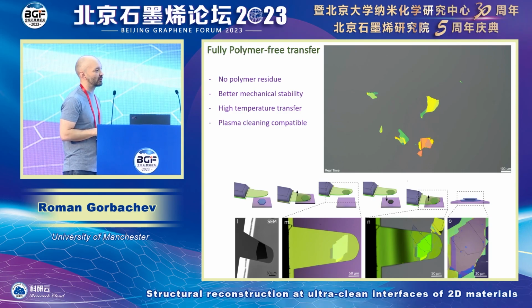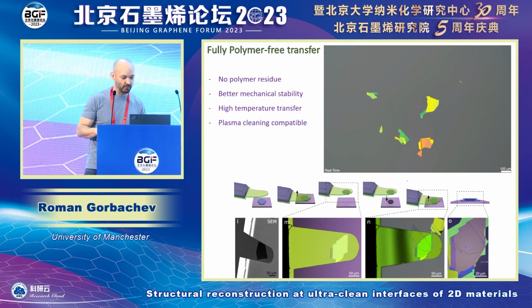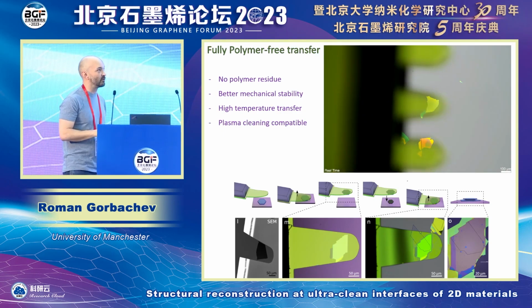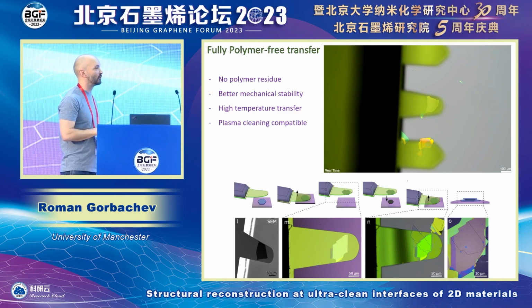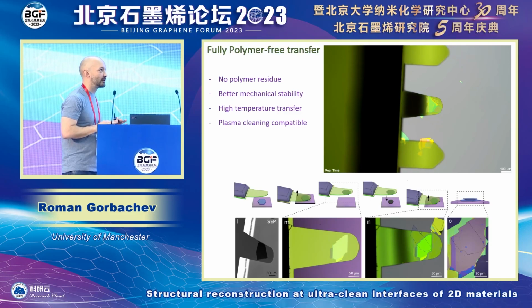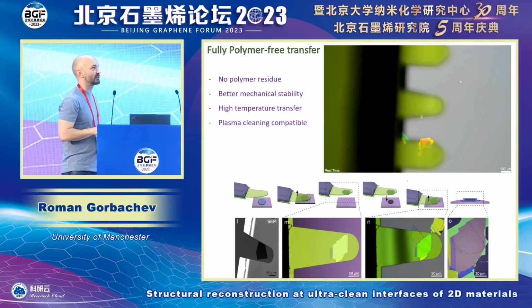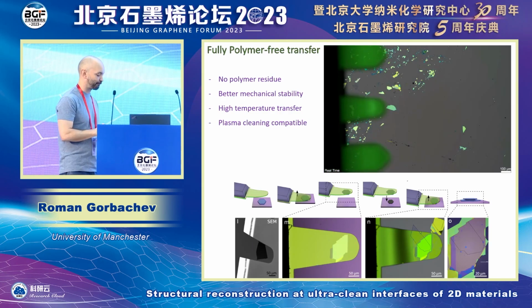And we basically just touch our crystals with this cantilever, and then we pick it up and we move to another one, assembling step by step, the same way as we've been doing this with polymers, only this time it is a lot faster because now we can use it at a very high temperature. We can put up to 300, 350 degrees, and you can see this is like a live recording of a stacking, and we don't really control the speed of lamination. We don't really worry about all of these problems with polymers. It becomes a lot easier to do.